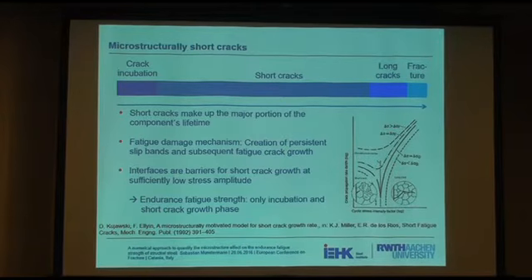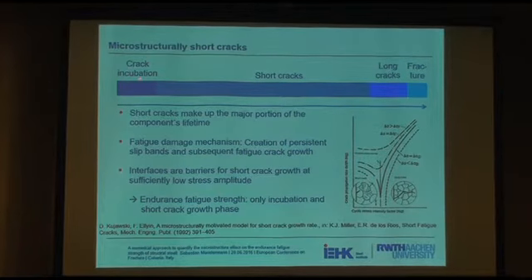Okay, to understand how we can express this, we also need to understand the fatigue mechanisms of steel, especially in the early fatigue stages. So you can here see an illustration of the total lifetime of a component under cyclic loads. And you see that we've got a crack incubation phase. This is a phase on very, very small length scales. The first cracks are formed. Usually that happens, or that can happen, at inclusions.